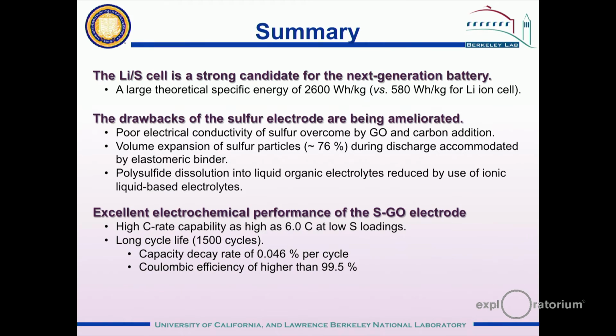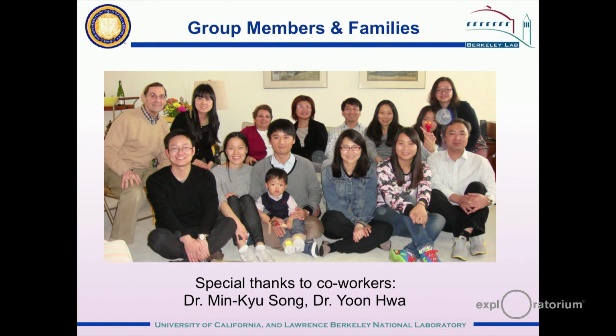So we think that the lithium sulfur cell is a very strong candidate for the next generation of batteries after the lithium ion cells. There are difficulties in using sulfur, and I've already discussed those difficulties, and we think we've overcome them pretty well. And the sulfur graphene oxide electrode has already demonstrated very good performance, very high rate capability at low loadings, and very long cycle life. So we think this is quite a promising technology.